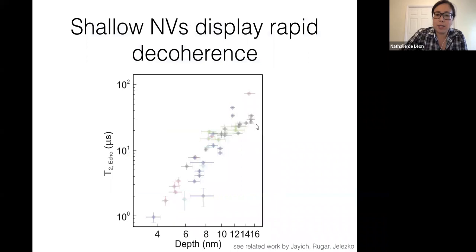The reason that we know this is that if you look at NV centers and just plot their spin coherence time as a function of distance away from the surface, deep in the bulk, you get T2s of something like a few milliseconds. But then as you approach the surface within about 100 nanometers, you get this precipitous decline of the spin coherence. And by the time you get to within a few nanometers of the surface, your spin coherence is more like a few hundred nanoseconds. So this is actually pretty severe scaling and a real limitation for any of these schemes to try to deploy NV centers in the single molecule imaging work.